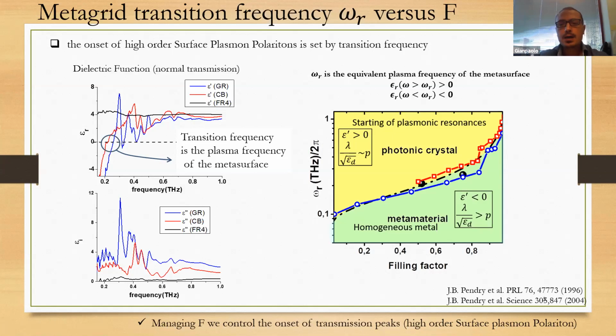Above this frequency, we see the onset of high-order plasmonic excitations, since the dielectric function of the metasurface is positive, and the wavelength starts to be comparable. I mean, the wavelengths at the interface. The wavelength at the metallic-insulator interface is scaled by the dielectric constant of the substrate. We see the onset of this peak. The dielectric constant of the metasurfaces is positive.